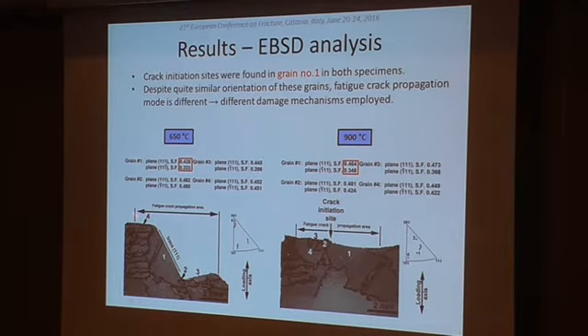Here I put two specimens to show the example of different mechanism. Here is one axial section from a specimen from fatigue test at 650 centigrades. Here is from 900 centigrades. Fatigue crack initiated in both cases in grain number 1. In this case, the grains were almost identically oriented with planes with almost the same Schmid factor, and you can see that the behavior of the crack was quite different at both temperatures. So therefore, there is really some different mechanism going on.